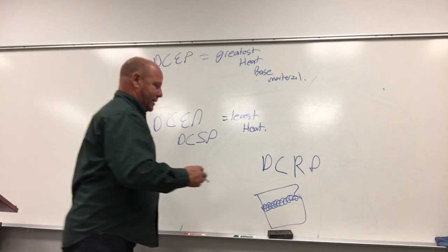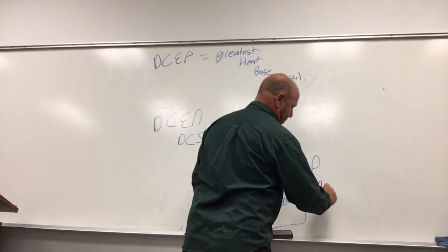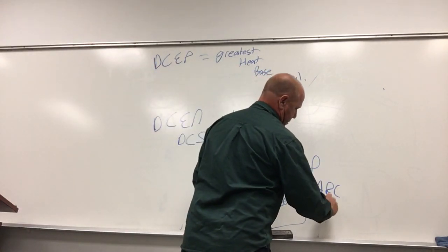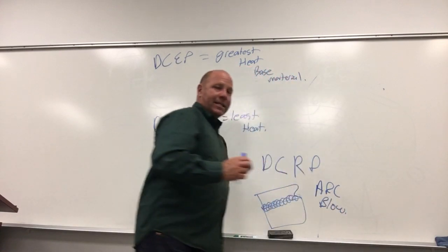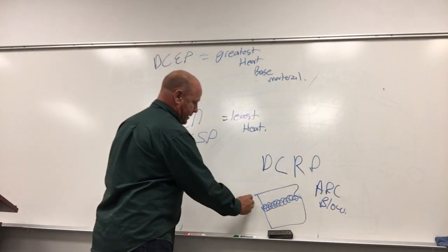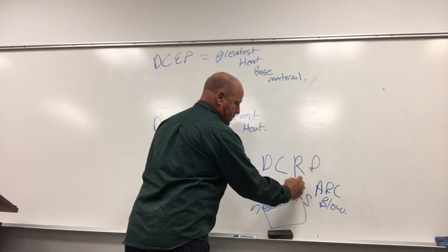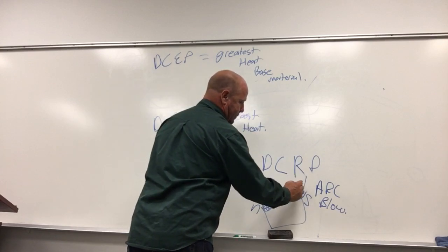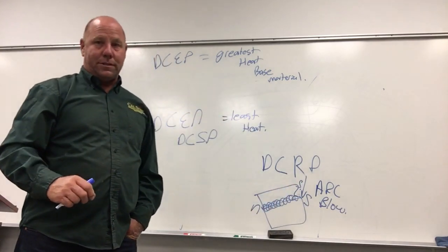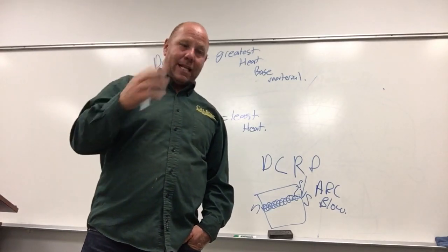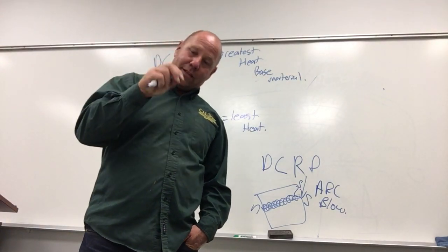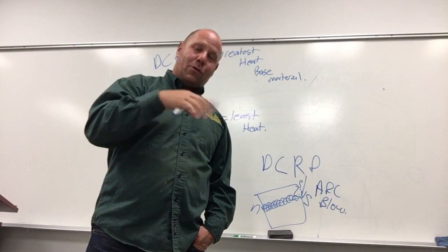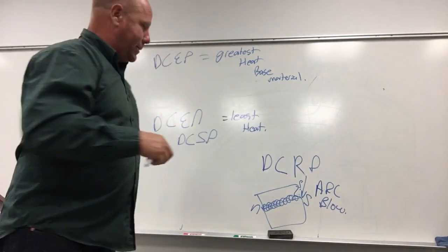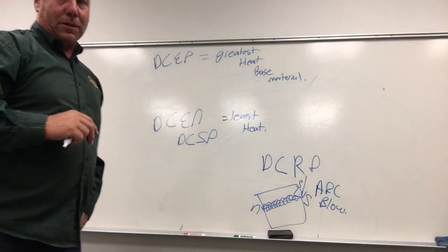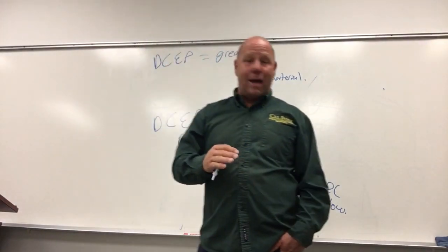This particular effect is called arc blow. It's because you've charged your plates, and as you reach the end, you end up with two of the same poles, and they end up repelling that electron off. So instead of that little ball of material coming across the plate, it gets blown off and it starts making more spatter and some of the debris. That's called arc blow.